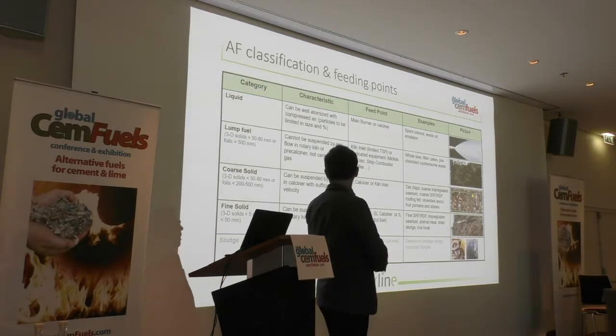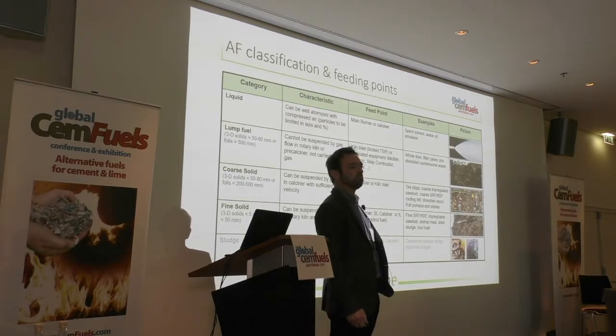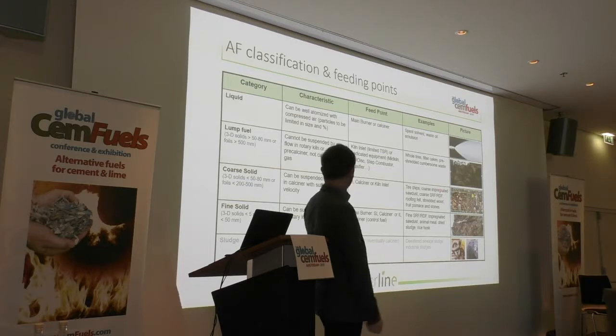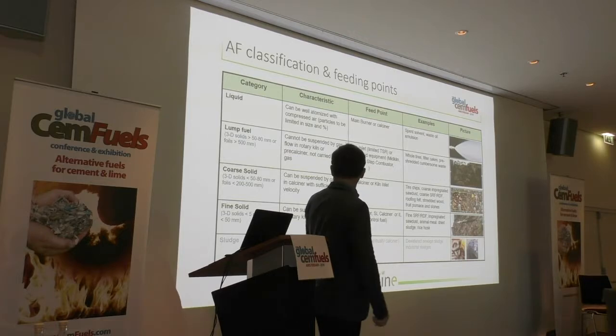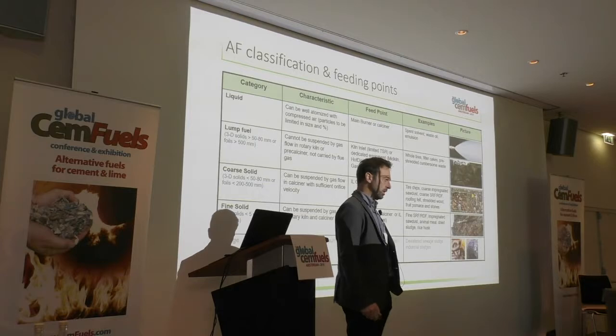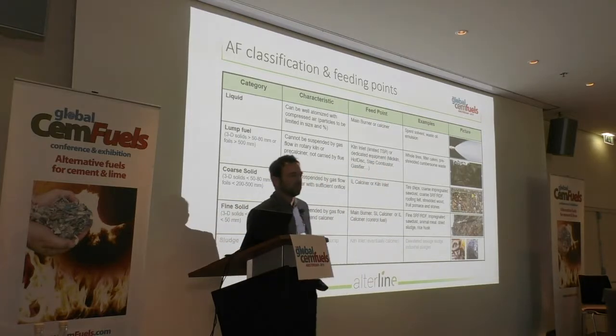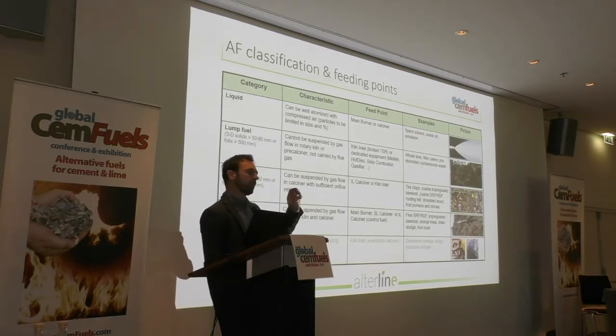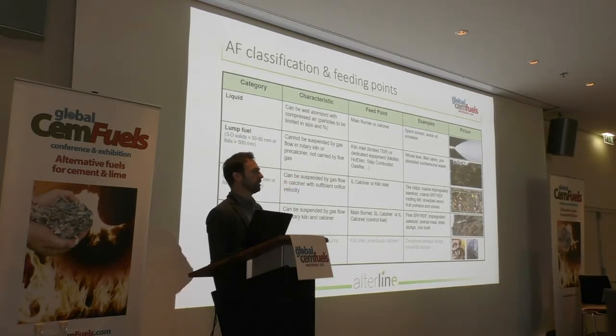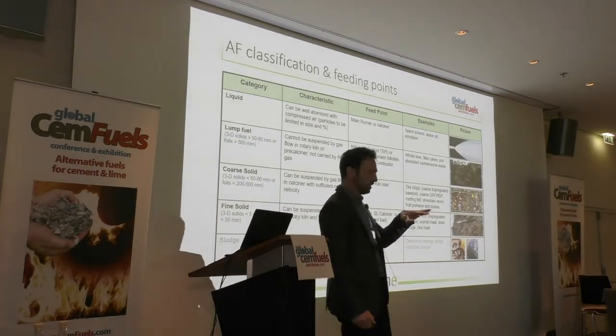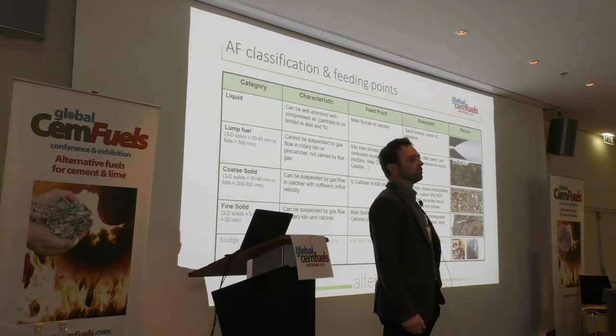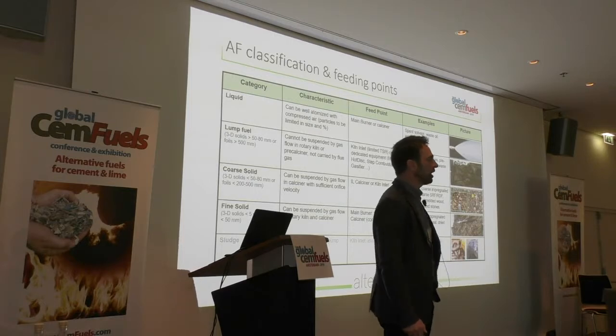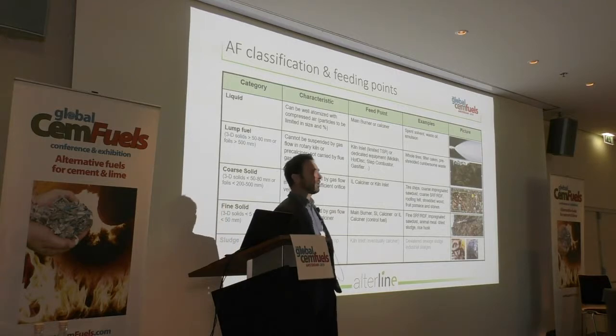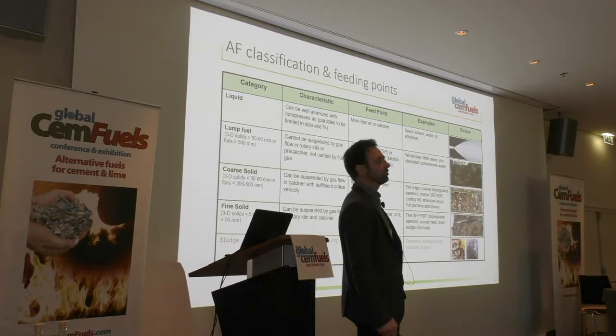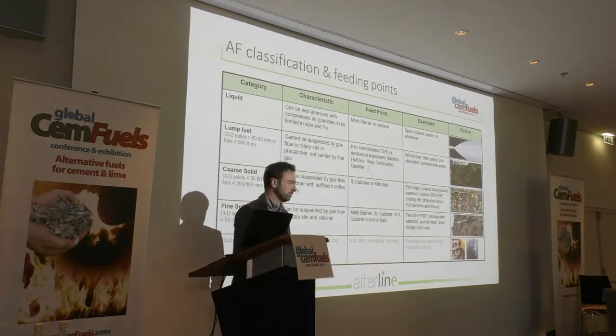That's for calciner. It's coarse solids, typically tire chips, coarse SRF, this type of product. Shredded wood really depends on the calciner design, I mean inline calciner. And then fine solids for separate line calciner or pneumatic, so main burner, pneumatic injection. That's basically below 5 millimeters for the 3D particles, and 2D particles can be 20, 30, 50 millimeters. I have sometimes a quite different opinion than some SRF suppliers I heard earlier. To my opinion, the really good fuel for the main burner is mainly to have light material and avoid 3D or heavy particles, much more than the size of the 2D particles, which has finally low impact. It doesn't make really difference if you have sheets of 20 millimeters or 30 millimeters or 35.